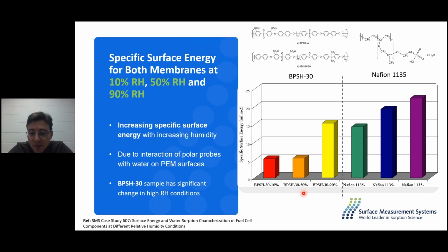And we can see that, quite interestingly, our BPSH30 is quite resistant to humidity until it gets to 90% RH, at which point the specific surface energy triples. So we're having a really large increase and an activity step under those more saturated conditions. Whereas our Nafion 1135 has a more linear relationship with relative humidity. Now we can see that its specific surface energy is increasing at somewhat of a steady rate as we're introducing that different relative humidity.